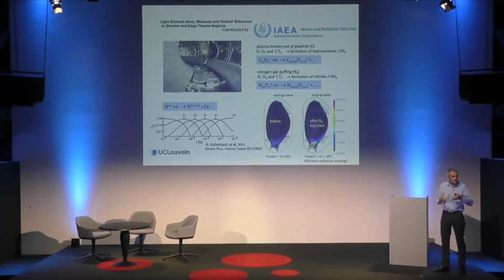Okay, this problem of wall erosion was sort of circumvented with the plasma limiters, and the first ones were carbon, so graphite, if you like. And this carbon, as was mentioned, was a nasty component to introduce in the plasma because that would form hydrocarbons, and these hydrocarbons would end up with kind of tar that would contain tritium in the end. So that was very bad.